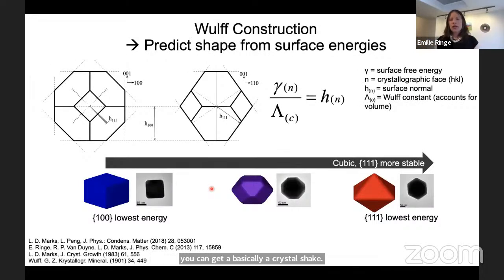This is encoded in what's called the Wulff construction, which is a construction to predict shape from surface energy. In its very simple form, which is basically the single crystal form, you're basically just going to say that your h, which is the distance from the center of a crystal to a facet, is proportional, modulo a proportionality constant, to the surface energy of that facet. So if you have very low 100 surface energy in a cubic crystal, you're going to get a cube. And if you have low 111, you're going to get an octahedron.